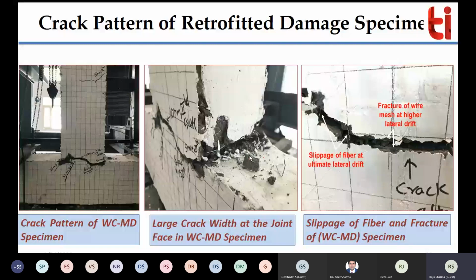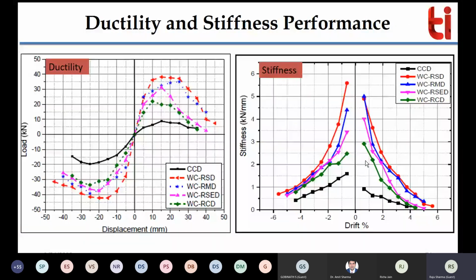Right? And you can see the crimped hooked fiber over in the second image, right? So you can see the fracture of wire mesh at higher lateral drift. Also there is a failure of the wire mesh, which actually provides the confinement, and that would be the reason for the complete failure of the specimen, right? So this is the kind of cracks which we got from the specimen.